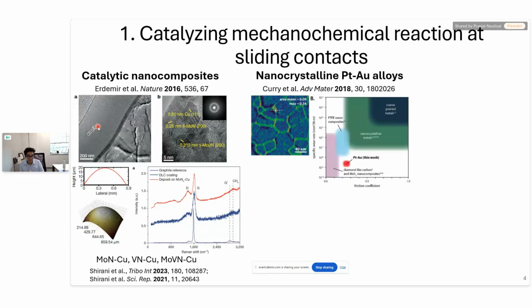And here I'm showing you the specific wear rate on the y-axis versus friction coefficient on the x-axis. And they observed that the wear resistance of these platinum-gold alloys was extremely impressive, surpassing the performance of most engineering alloys, and actually matching up to diamond-like carbon coatings, which are known for their excellent anti-wear properties.